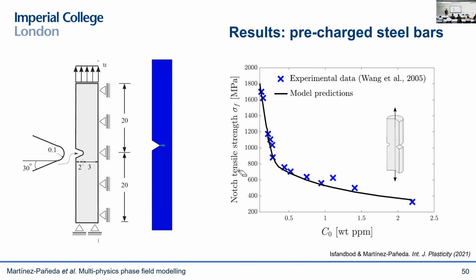But we can also be quantitative. This is a comparison with experiments on pre-charged steel bars. These are high-strength steel bars. And you can see that we get a very good agreement in terms of notch tensile strength with experiments. So no fitting parameters whatsoever, and quite a good agreement there.